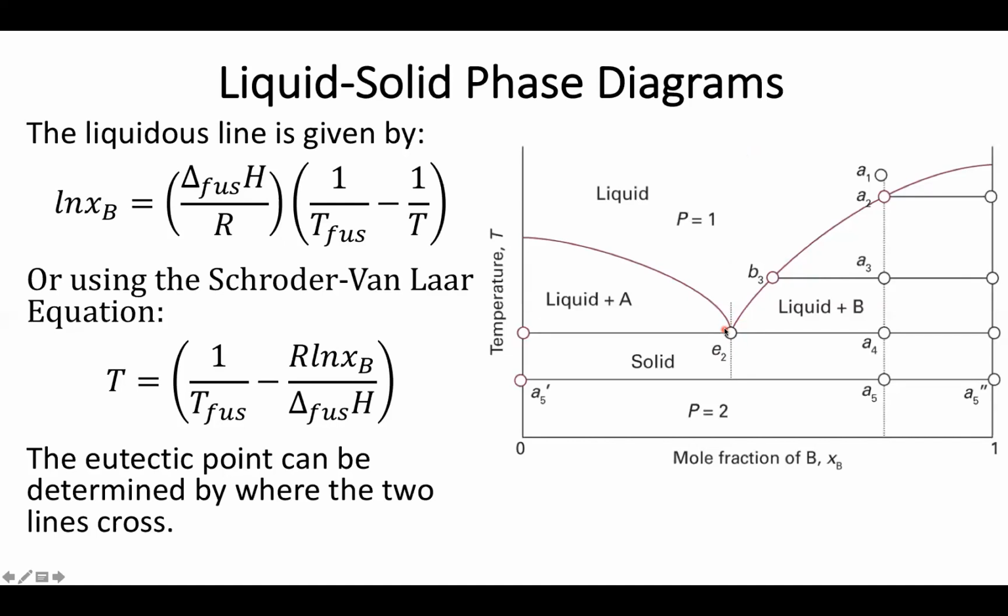And this means that you can actually get liquid water all the way down to about negative 21 degrees C before it freezes. Again, entirely based on its phase diagram and trying to get as close to the eutectic point as possible. However, as soon as you reach the eutectic point, we're going to essentially completely solidify everything out by making our pure solid A and pure solid B.